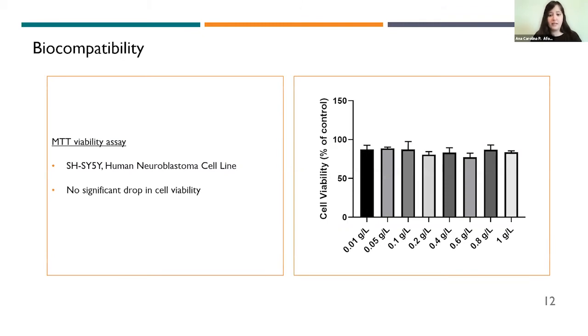We also assessed its biocompatibility by adding the carbon dot to human cells in increasing concentration for 48 hours, and the cell viability was determined via an MTT viability assay. There was no significant drop in cellular viability. Thus, our results indicate that the carbon dot is indeed compatible with human cells, and so can be of potential use for intracellular pH measurements in biological applications.